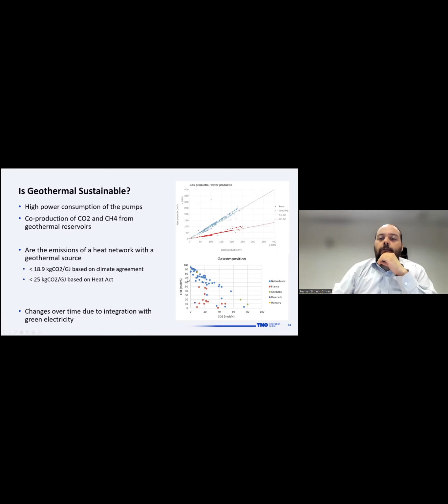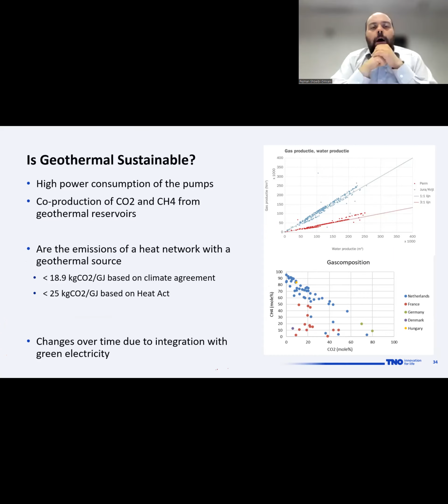I can show you the ratio of natural gas to CO2 for the different countries. And you can see in the Netherlands, there is a large amount of natural gas being produced by the geothermal fluid, and the ratio is also high. In some of the formations in the Netherlands, for every cubic meter of water that you produce, you also produce one cubic meter of gas. So if you're producing 200 cubic meters per hour of brine, you're producing 200 cubic meters per hour of gas. So is it actually sustainable?